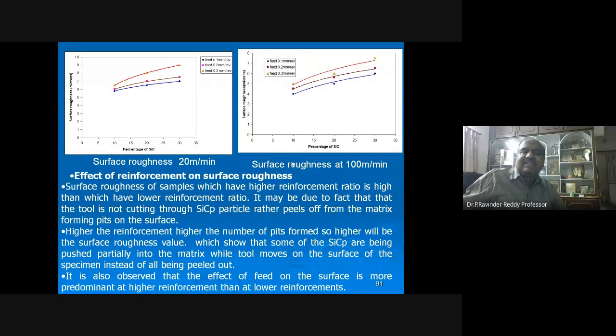The surface roughness at 20 meters per minute and at 100 meters per minute, at different cutting speeds and changing feed rate, and the same at different percentages of silicon carbide particulates. Surface roughness is higher for samples which have a higher reinforcement ratio than for those with a lower reinforcement ratio. It may be due to the fact that the tool is not cutting through the silicon carbide particulate but rather peels it off